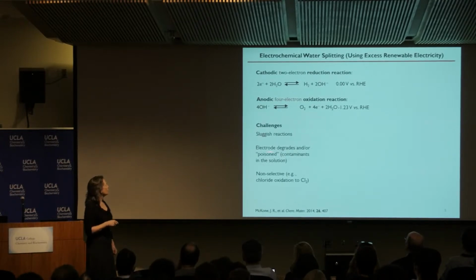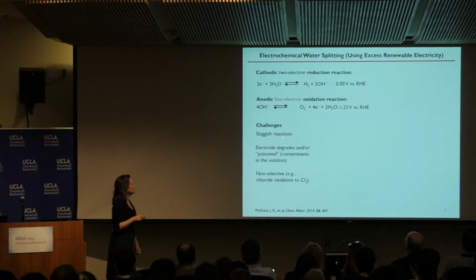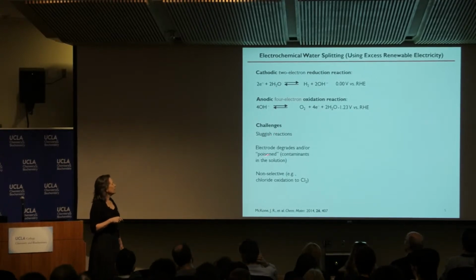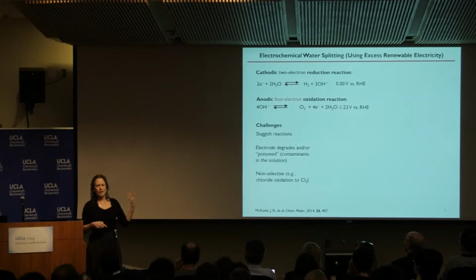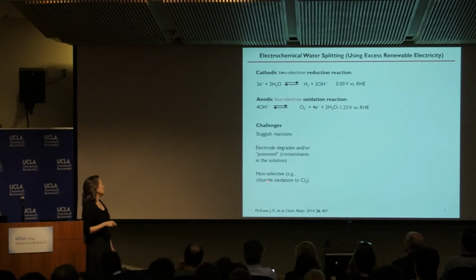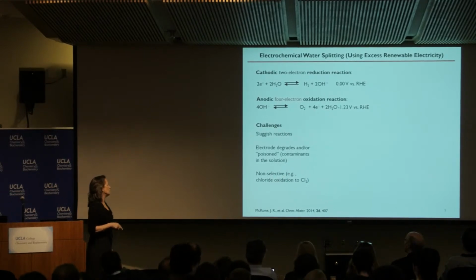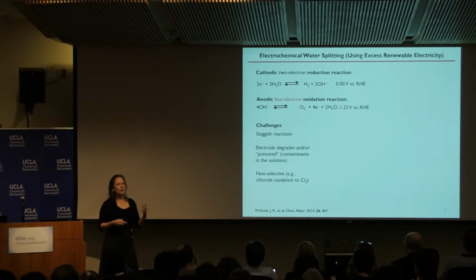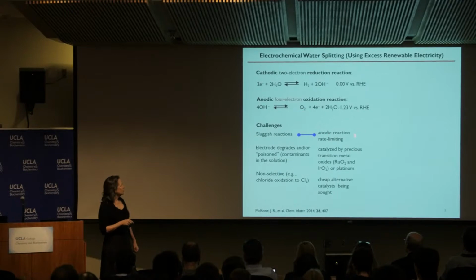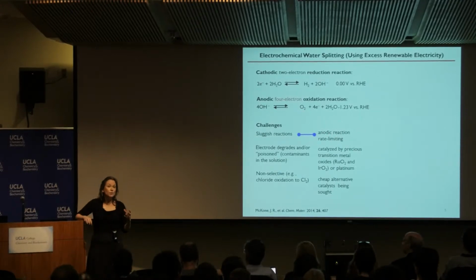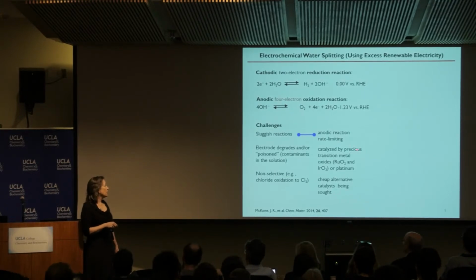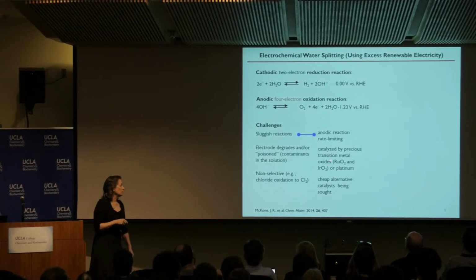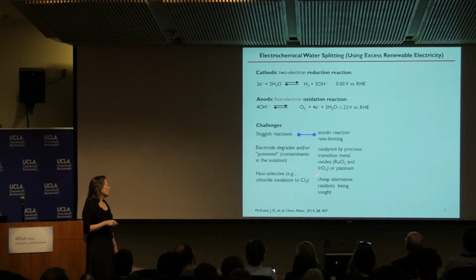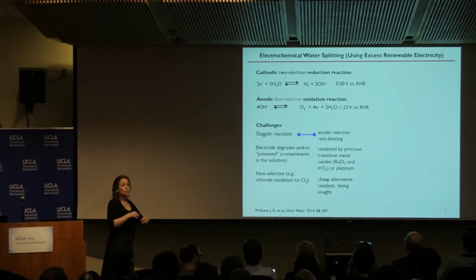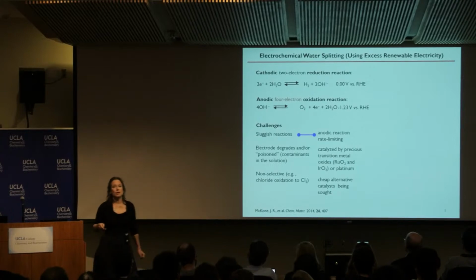And here are written some of the challenges. The reactions are slow. It's a 4-electron oxidation. You have problems with the electrode in terms of it degrading or being poisoned. If you have, for example, ions, it can be non-selective. So you can't just stick seawater in there and expect to get out oxygen and split water. It'll oxidize chloride and make chlorine, for example. So how do we go about thinking about this problem? Well, as I already said, the anode reaction is rate limiting, and we know that one can do it well and even do it selectively if you use very, very precious transition metal oxides such as iridium oxide and ruthenium oxide, or platinum. And so there's a lot of interest in finding cheap alternative catalysts that could be widely deployed, because you're not going to widely deploy those catalysts very easily.